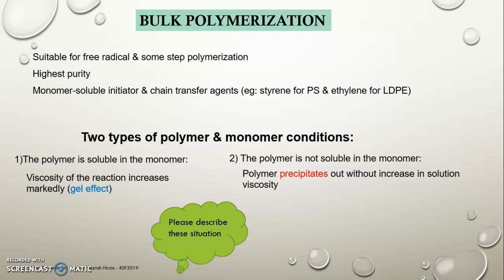The other name for the gel effect is the Trommsdorff effect. In this case, the molar mass distribution of the product can change, or the polymer becomes discolored as a result of oxidation or decomposition. One solution is to interrupt the polymerization at a conversion of 40 to 60% and recycle the residual monomer. So we have to avoid the gel effect.